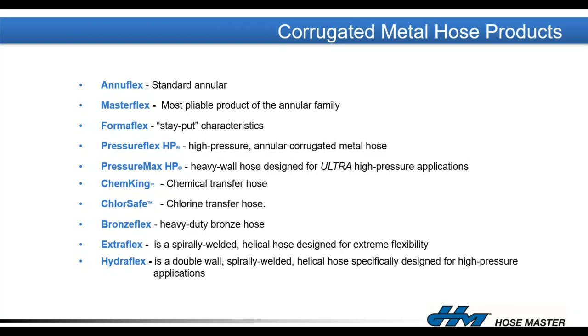For higher pressures, we can make our products out of heavier wall thicknesses. And that's our Pressure Flex for high pressures or Pressure Max HP. That Pressure Max HP is a great product. There's just nothing in the industry that can handle the combination of high pressures and maintain flexibility in terms of a nice tight bend radius. There are hoses out there that may have higher pressure ratings, but they become very, very stiff. They're hard to bend, they have low cycle life, and Pressure Max HP is just the best combination of flexibility as well as high pressure rating.